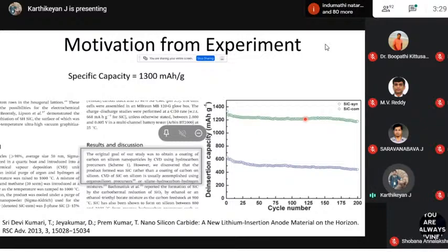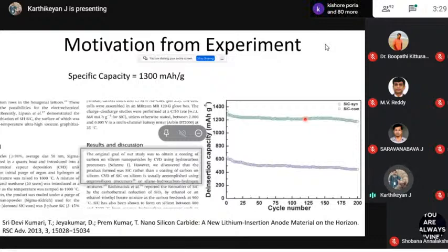They were not understanding what is really happening in the silicon carbide nanoparticle, because silicon carbides are insulators, right? Usually we don't use an insulator in electrode material, but here surprisingly they got a very good capacity for silicon carbide, and they started asking us to understand what is really happening in the silicon carbide nanoparticle. So we again started making a toy model kind of thing.